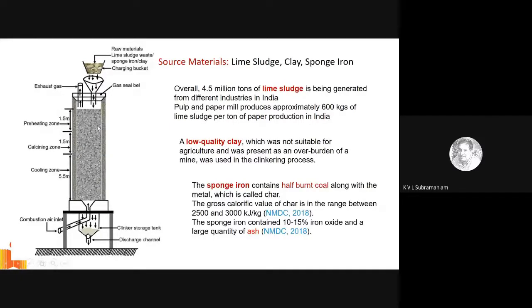the material that is passing through the kiln. Now, all of those objectives are achieved in this vertical kiln, where basically at the bottom end, the temperature was as high as 1500 degrees Celsius. At the top end, we were basically introducing the raw material. And the material slowly moved through the drum, because as we emptied out the clinker that was forming out, the material would slowly move in. And we could slowly move the entire material through the vertical kiln so that it went through this slow process of cooking, which allowed the calcium to separate out from the raw material, the silica to separate out from the raw material, the alumina to separate out from the raw material.